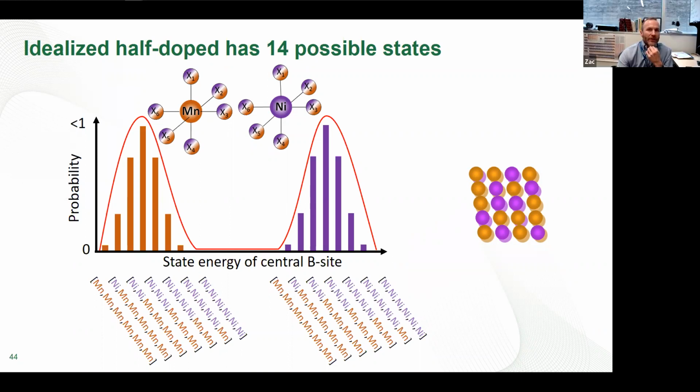Well, the materials that we make with PLD are in such a highly out-of-equilibrium state when we hit them with the laser, and it quenches so quickly, that from all of our microscopy it looks like, at least with that particular growth process, you really do get completely mixed. You lock in the super highly disordered state.